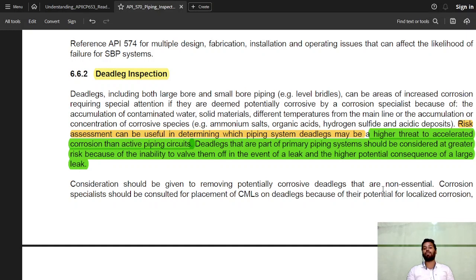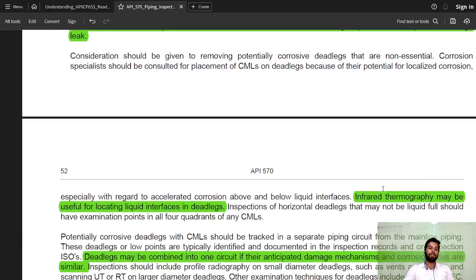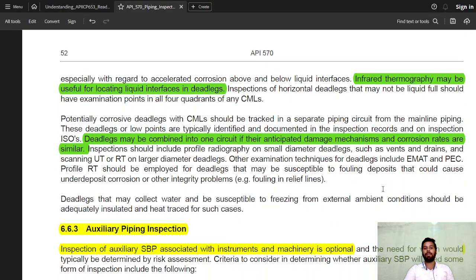Risk assessment can be useful in determining which piping system dead legs may be a higher threat to accelerated corrosion than active piping circuits. Dead legs that are a part of the primary piping system should be considered at greater risk because of the inability to valve them off in the event of a leak and a higher potential consequence of the larger leak. Infrared thermography may be useful for locating liquid interfaces in the dead legs. Dead legs may be combined into one circuit if their anticipated damage mechanisms and corrosion rates are similar.